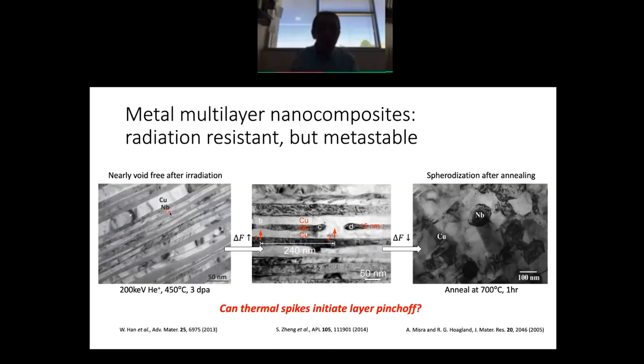Well, the reason why it's metastable is because if you were to take a perfect layer, just a continuous layer of copper and niobium, those kinds of layers are not subject to morphological instability, such as the Rayleigh-Taylor instability that would plague, let's say, cylindrical shaped features, right? So continuous layers are actually metastable. If you wanted to pinch off a layer, there is an energy barrier that has to be overcome to do that, right? Nevertheless, we do see occasionally that these layers pinch off. So here's an example of a micrograph of a layer that is pinched off.